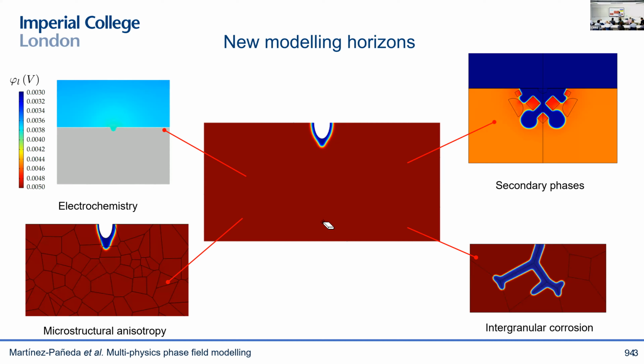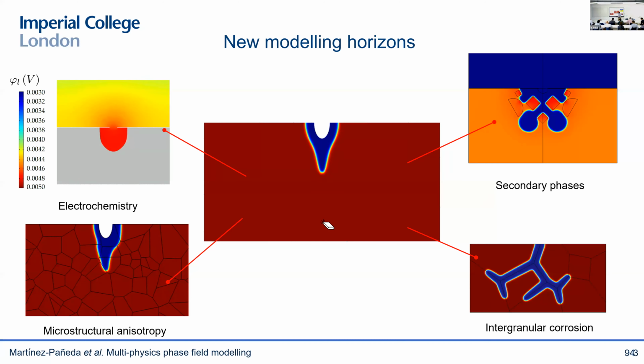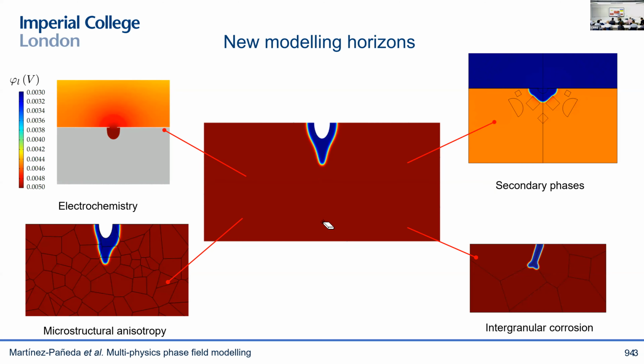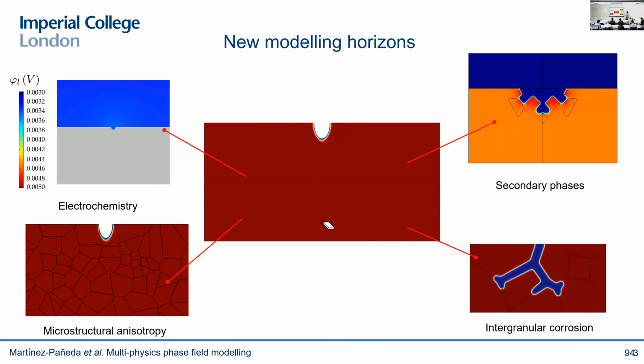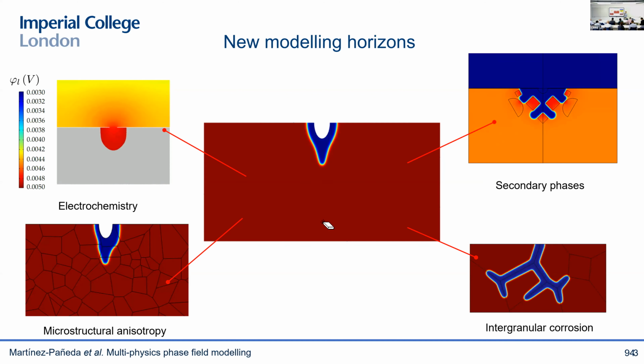So for example, you can capture here the effect of the electrochemistry. We know the electrochemistry plays a big role, but we can simulate the electrochemistry. We can capture the effect of the microstructural anisotropy, not only on the mechanical behavior, but also on the corrosion behavior. We can capture also the effect of secondary phases. So you can see we capture complex corrosion processes and even intergranular corrosion. And we can couple this with our previous formulations of fracture, fatigue, and so on and so forth.